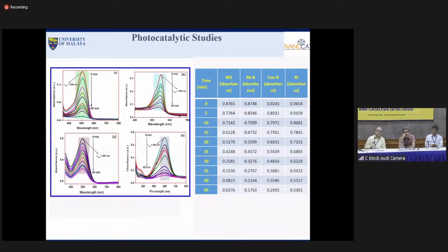Now we performed the photocatalytic activity. We used four organic industrial dyes: malachite green, rhodamine B, Congo red, and red ink. We tested the photocatalytic efficiency of the prepared sample in aqueous medium. The photocatalytic reactions ran over a time interval of 0 to 45 minutes. From the figure, you can clearly understand that the absorption decreases with increasing time, and you can also see the values mentioned in the table. From the table, you can observe that the composite has activity against all the dyes.